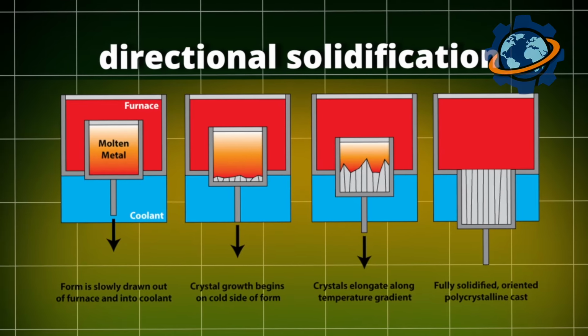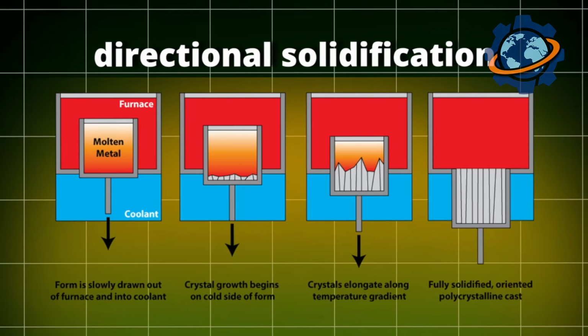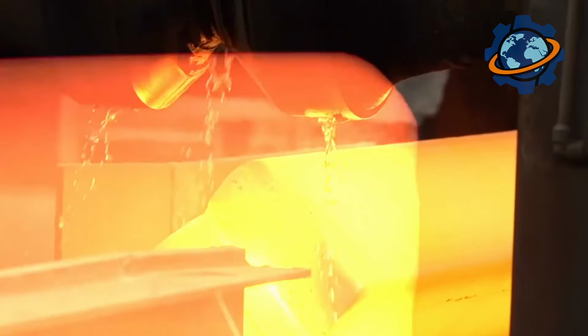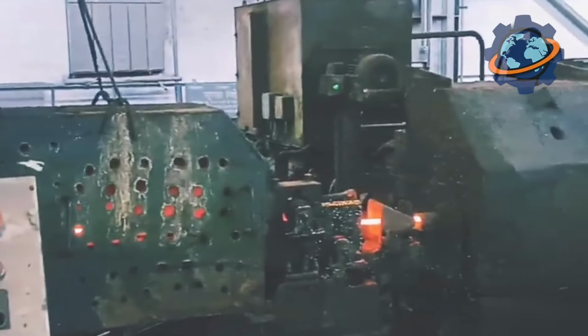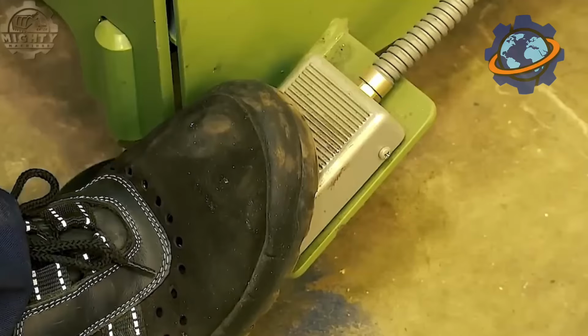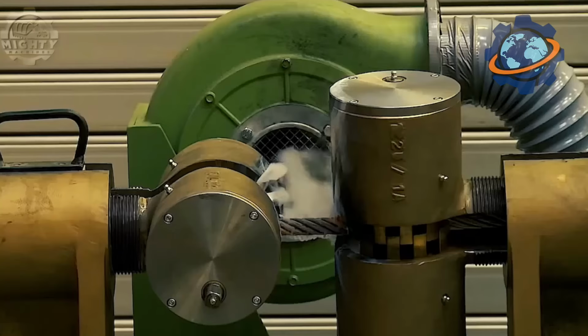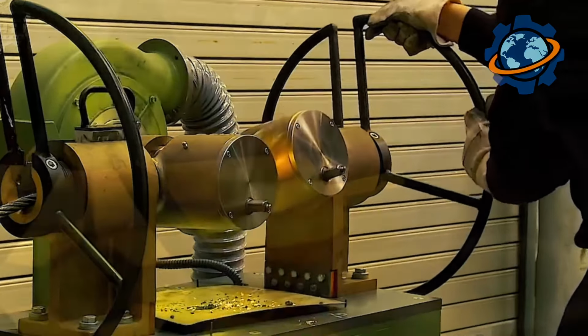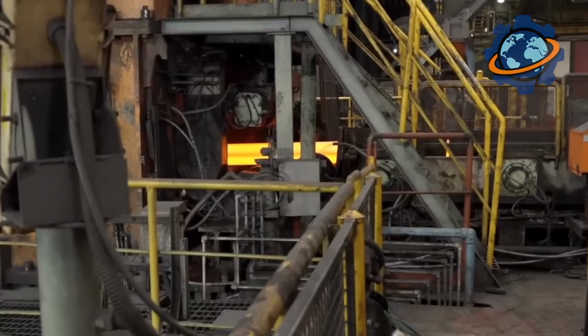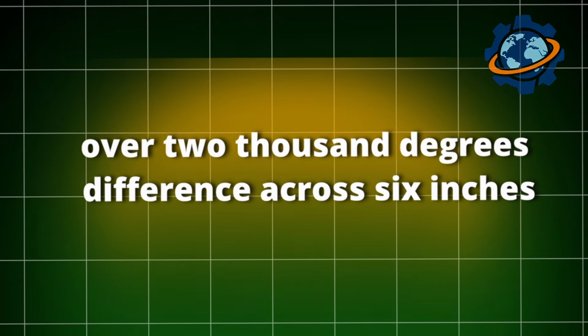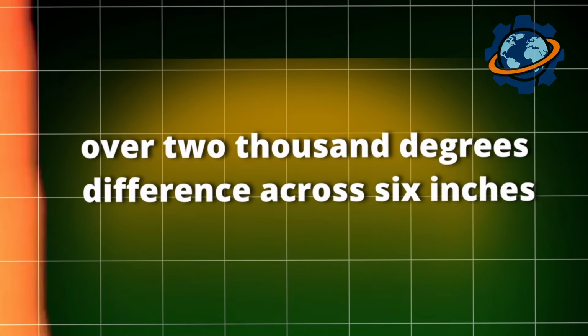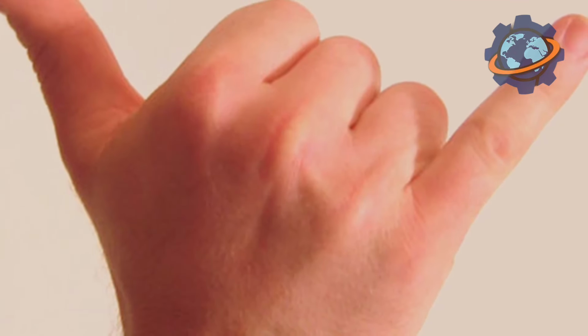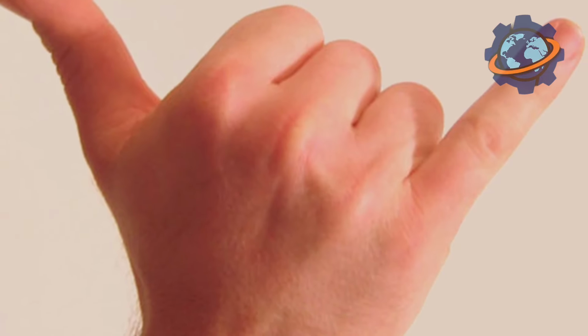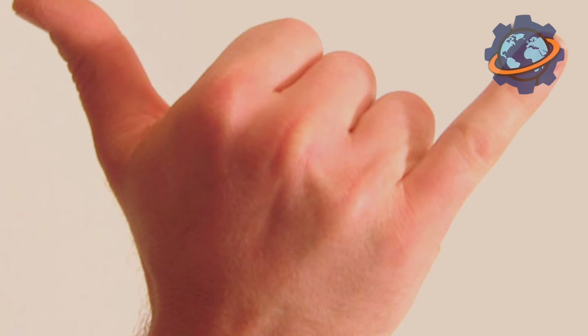Now comes the magic, directional solidification. The filled mold sits atop a water-cooled chill plate at 70 degrees Fahrenheit while surrounded by heating elements maintaining 2,400 degrees above. This creates the steepest temperature gradient in metallurgy, over 2,000 degrees difference across 6 inches. That's transitioning from Arctic to volcanic conditions in the space between your thumb and pinky.